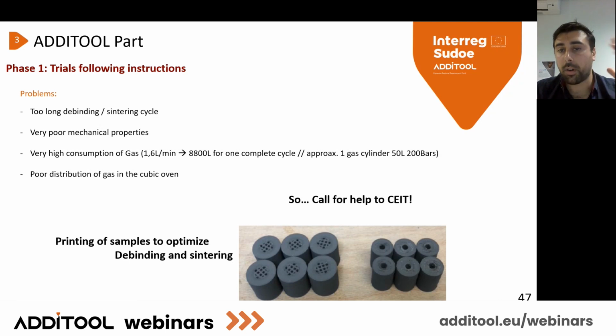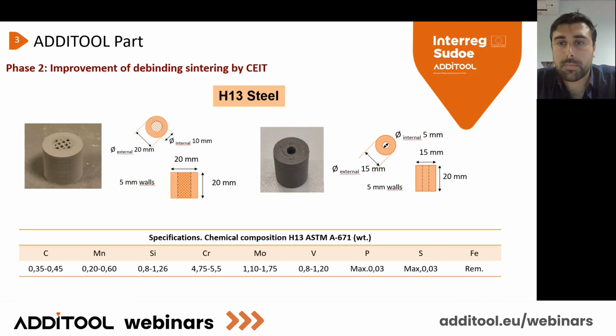So we called for help to CEIT, one of the partners of Additool, and they are experts on this kind of job: sintering, debinding, etc. It's their job. So we have printed a lot of samples to optimize this process. As I said, these were the specimens, 15 millimeters of diameter and 20 millimeters high. You have the composition of the H13. Remember, it's about 0.4% of carbon. And the objective of CEIT is to optimize exactly the debinding and the sintering to do something with this kind of filament.